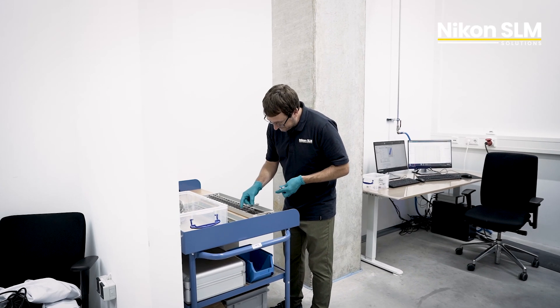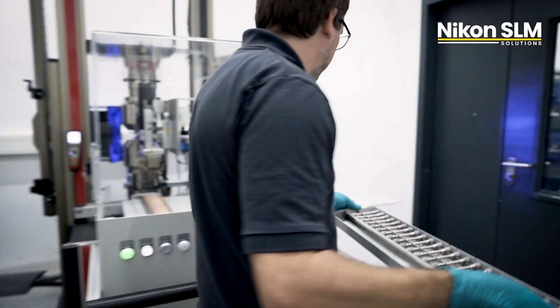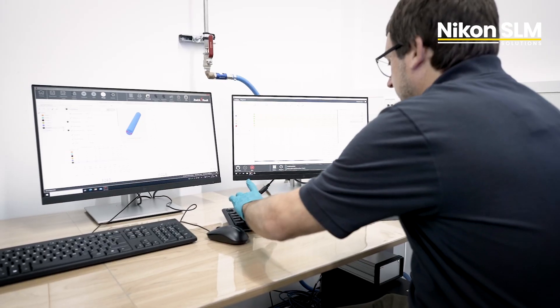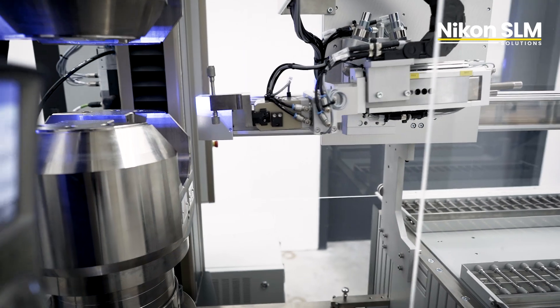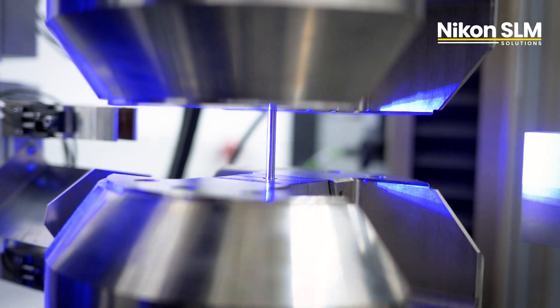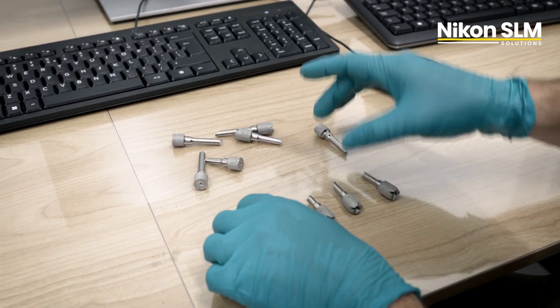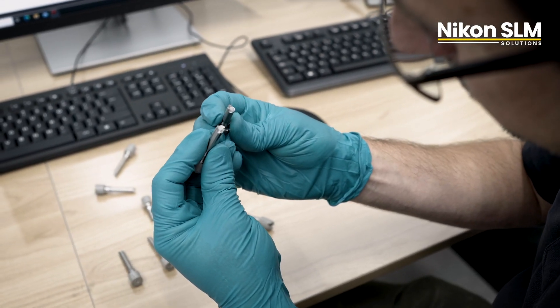This build job was already printed a year ago in Inconel 718 and was fully analyzed and validated. The results have actually exceeded our expectations. Over the full height from bottom to top, we have very stable material properties — for example, a yield strength of plus or minus 15 megapascal — which ensures that the applications our customers are printing are going to be very stable in terms of material performance.